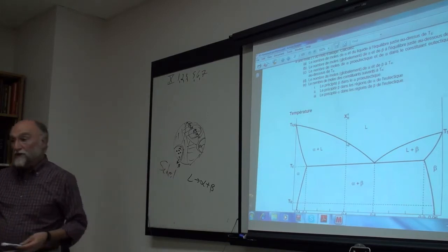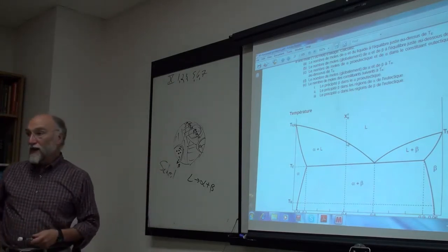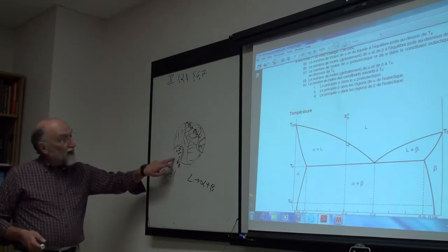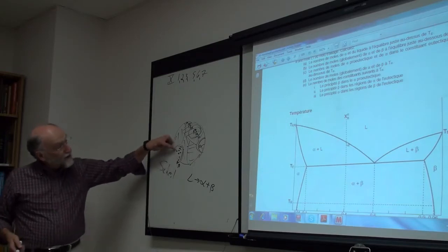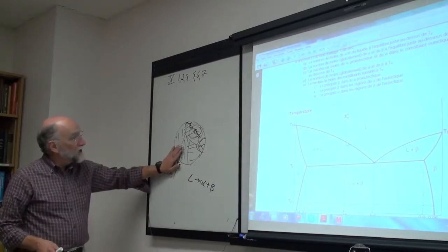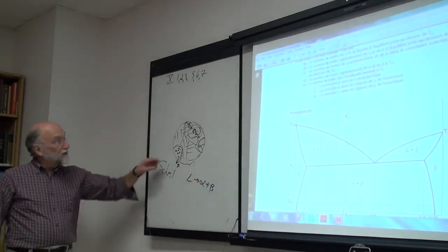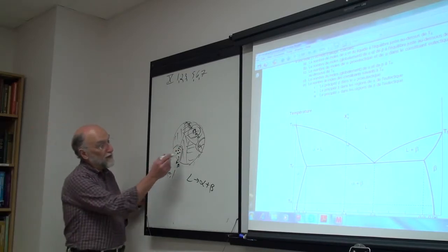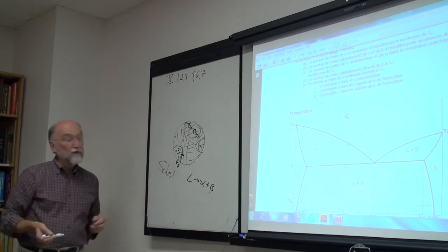This precipitation hardening is going to make the stuff much harder because dislocations get stopped by the precipitates. Okay, so this would be the beta precipitated in the alpha. What's left here is called the residual alpha. So at T eutectic, the alpha is homogeneous, one single phase at this composition. When you cool it down to TR, to a good approximation, the total amount of the alpha grain stays the same. Of course, we're making an assumption because as you cool it down, there could be reactions going on across the boundary here, but we assume that's relatively small.